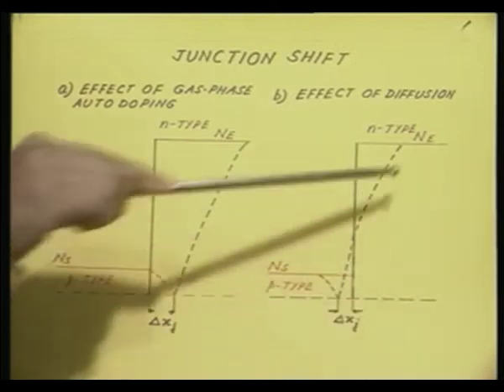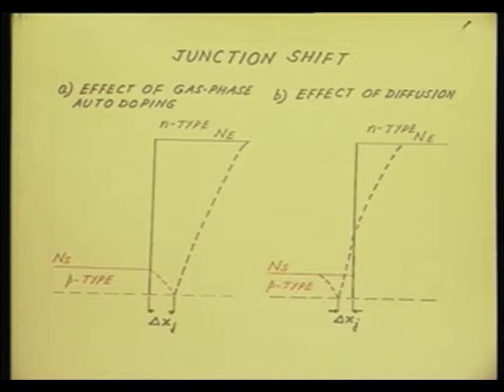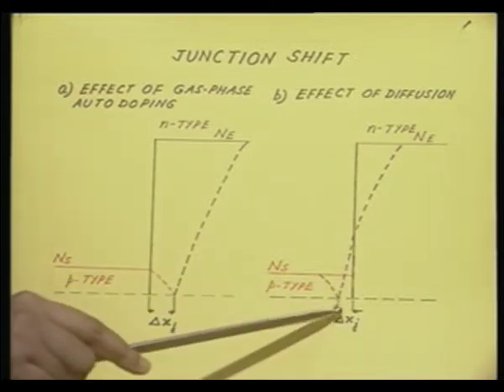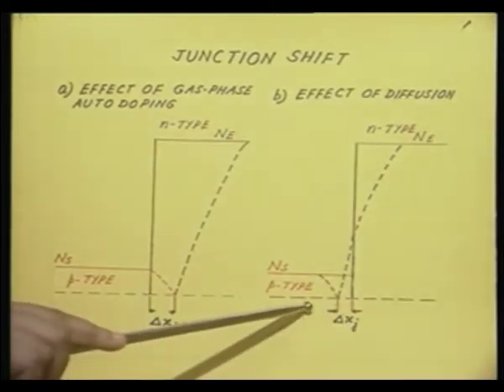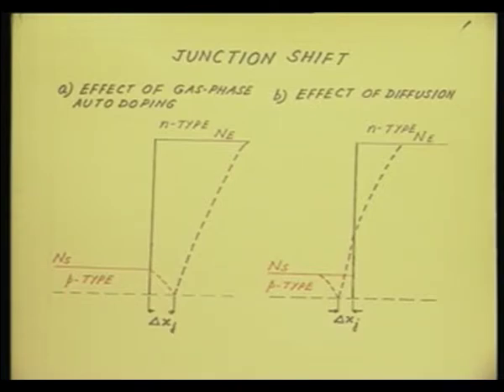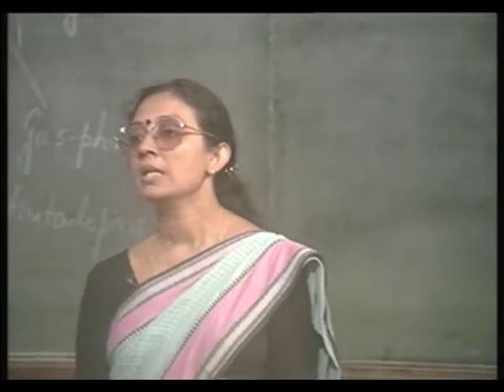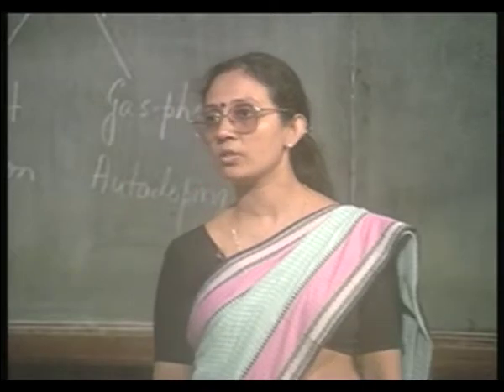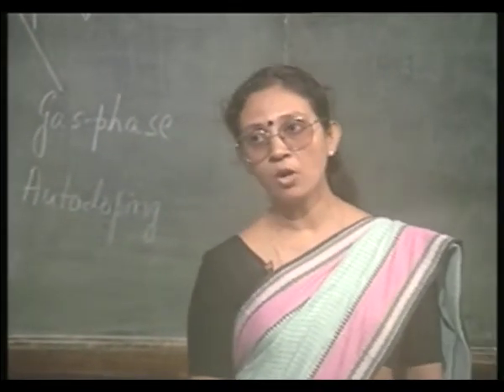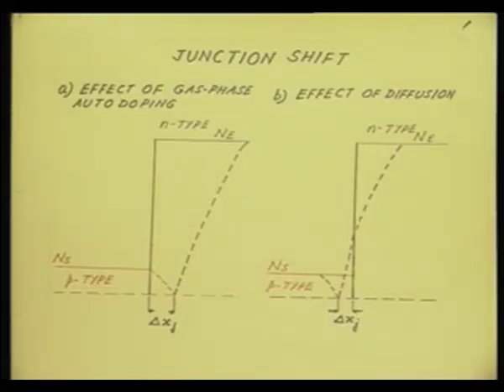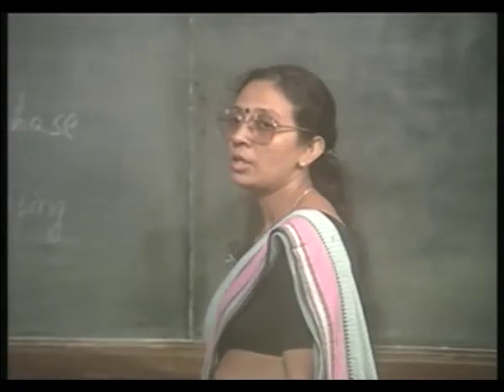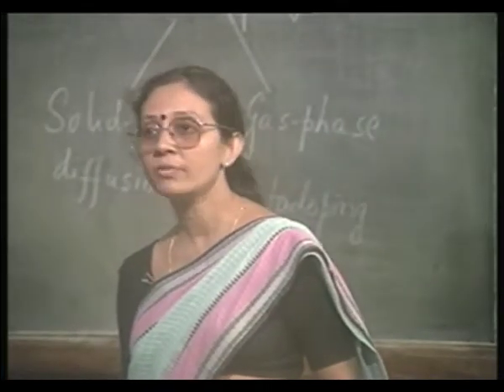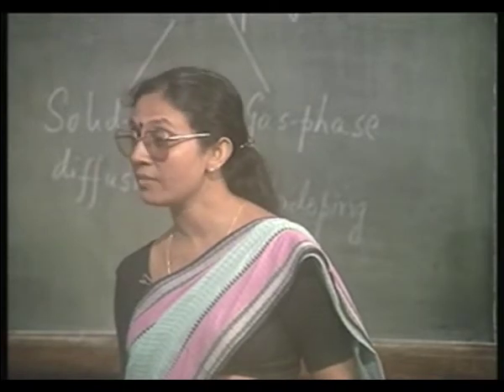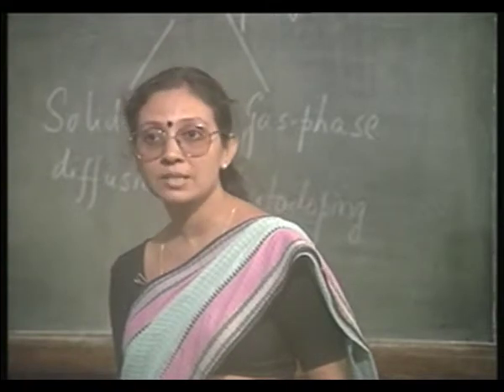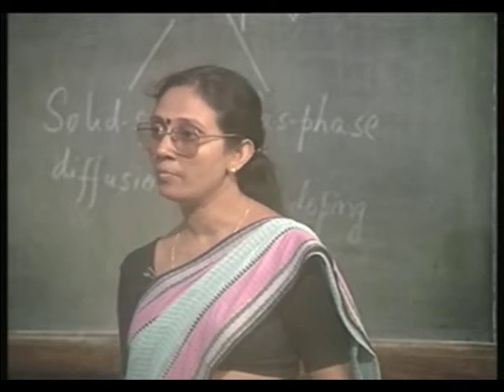P-type dopant is trying to move inside, n-type dopant is also trying to move inside the substrate. So, the junction shift is also present here, but notice that the junction has got shifted into the substrate, unlike in the previous case. These are, as I said, the results of computer simulation, in which we have tried to isolate one effect and study the effect of only that, either gas phase auto-doping or solid state diffusion. In a practical situation, you can understand that both these effects will be present. So, the junction shift will be dependent upon their relative dominance, which way the junction shifts. But that is a very important problem, that is the junction, the electronic junction may be shifted from the metallurgical junction.